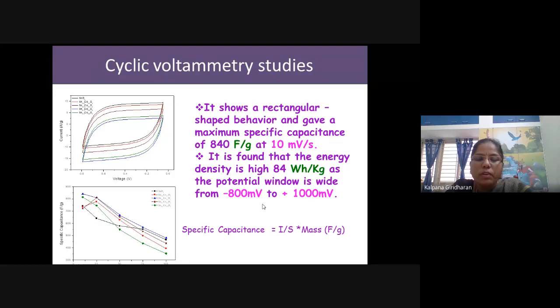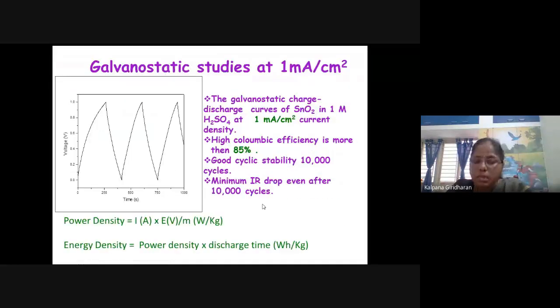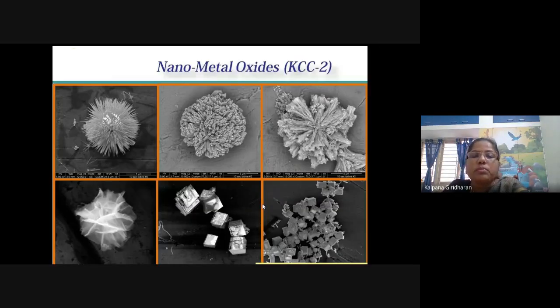We have obtained specific capacitance from current versus scan rate. This is a typical symmetrical charge-discharge cycle at 1 milliamp per centimeter current density in 1 molar sulfuric acid, giving a coulombic efficiency of 85% with good stability, run up to 10,000 cycles with minimum IR drop. The power density, energy density, and coulombic efficiency can be obtained from these equations.